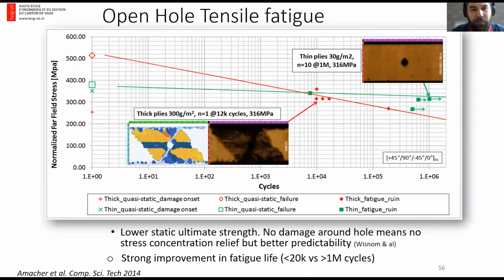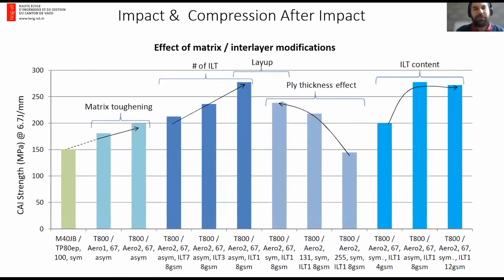And for transverse loading impact, we can reach fairly good impact properties and compression after impact properties with Thin-Ply. However, it has to be tuned, so we need to use interlayer toughening to reach very high values because we don't have much delamination. So we tend to have early fiber fracture, which is not a good type of failure mode to have in impact loading. Some other people, like a group in Girona and also in Porto, are working on hybrid ply thicknesses, where they use different ply thicknesses in the laminate, so that they can localize a controlled delamination during impact in order to still have delamination, but not too much.